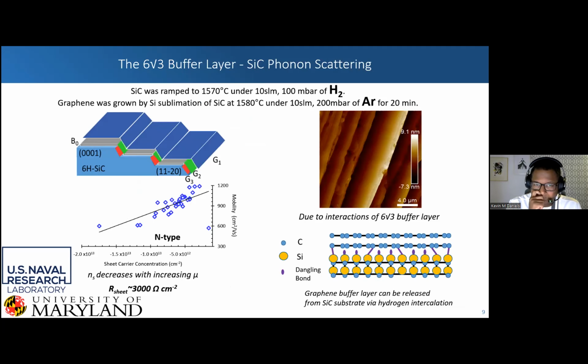Okay, so one of the biggest issues, however, with growing on the silicon face is contending with the 6√3 buffer layer. The 6√3 buffer layer is simply a carbon layer that is formed when you're desorbing your silicon, and that is covalently bound to your silicon carbide. What that causes is tons of phonon scattering, and the phonons of your graphene are tied to the phonons of your silicon carbide. So you can see here, our mobilities are nowhere near the theoretical 100,000 centimeters squared per volt second. It's just not there, mainly due to this electron-phonon coupling that we have.